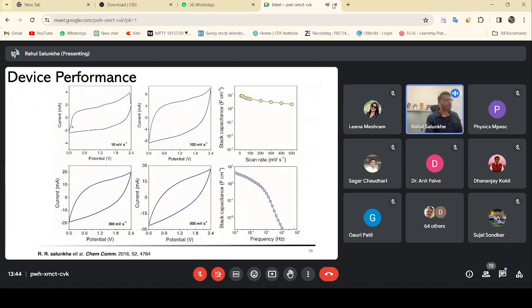And we can see that now we can go up to 2.4 volt with 10 millivolt per second, and this is 100 millivolt per second. We can see that the shape is quite good, retained very nicely up to 500 millivolt per second. And when we calculate the stack capacitance, that is the volumetric capacitance, we can see that it is around 10 farad per centimeter cube. If we compare this from the impedance analysis, depending upon the frequency we use, we can calculate the stack capacitance, and it is observed to be about the same, 10 farad per centimeter cube.